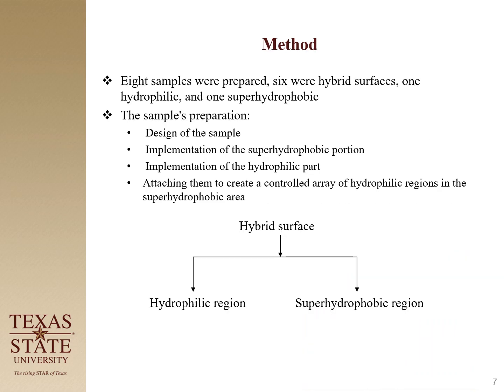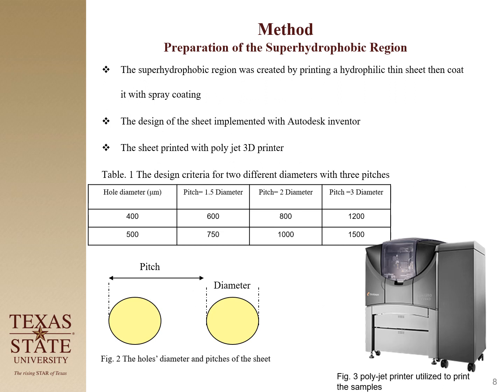For the method, I made 8 samples. Six samples were hybrid surfaces with 2 different diameters and 3 pitches between them. And then there are 2 samples: one is non-coated, so it will be hydrophilic, and the other is superhydrophobic only. And I compared them. My method is to create the hydrophilic region separately from the superhydrophobic region and then attach them together to have the hybrid surface.